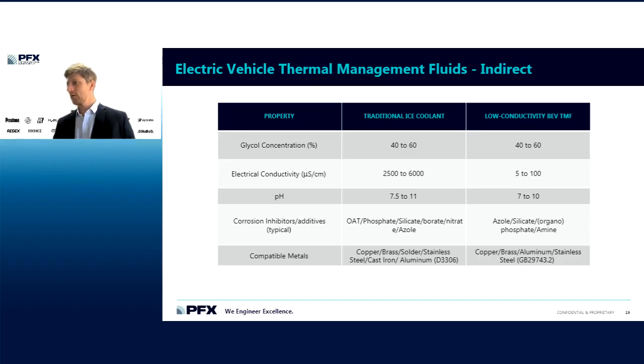conductivity. So we see a lot of things like azoles, some silicate, phosphate or organophosphate, and commonly we see the inclusion of amine, which allows you to get that increased basicity, increased RA, without having to use something like hydroxide, which is going to be a big contributor to electrical conductivity.